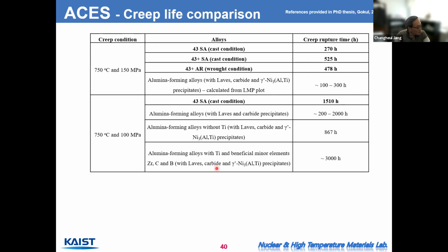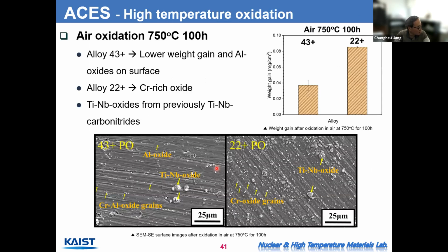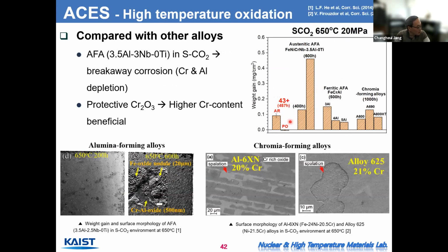So with that comparable creep resistance, we compare the oxidation resistance. So this is the oxidation resistance of one of the alloys we developed, and this is a comparison of our alloy shown here and the AFA alloys. In the supercritical CO2 environment, we have roughly 3 or 4 times lower weight gains, and that weight gain becomes even lower when we have a pre-oxidation.